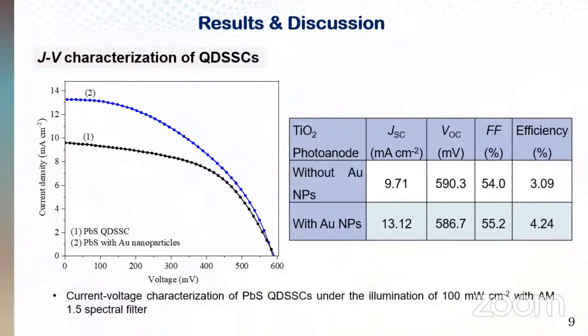According to the photovoltaic parameters summarized in Table 1, QDSSC with gold nanoparticles shows 13.12 mA per square centimeter current density, while QDSSC without gold nanoparticles shows only 9.71 mA per square centimeter current density, while the overall power conversion efficiency of the device has increased to 4.24% from the 3.09% of QDSSC without gold nanoparticles.